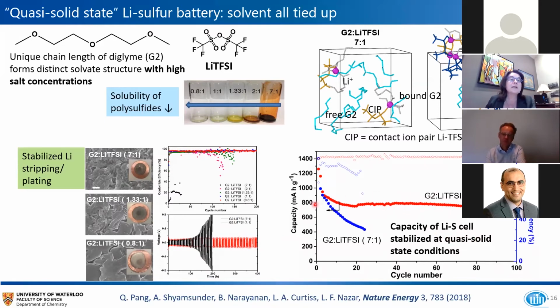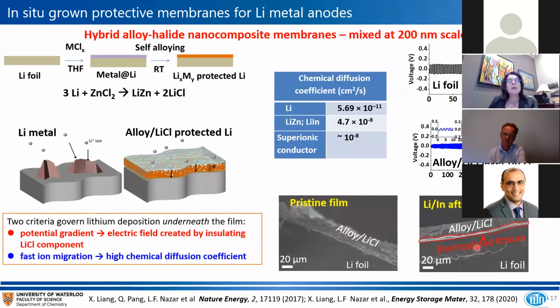So you notice the capacity isn't outstanding. It's not up here at 1,000, but this is, as I said, almost pure solid state conditions. So this gave us certainly some hope. And so then in parallel, we also started working on trying to develop membranes for lithium metal anodes, just sort of as another route to stabilizing the lithium metal.